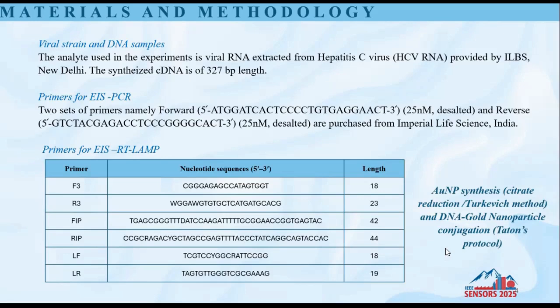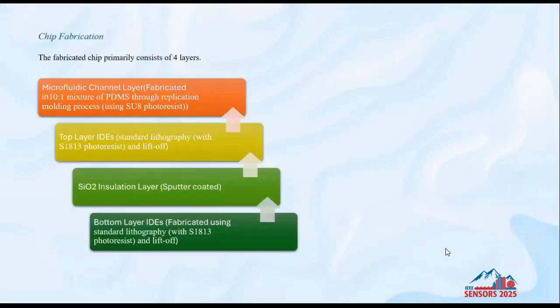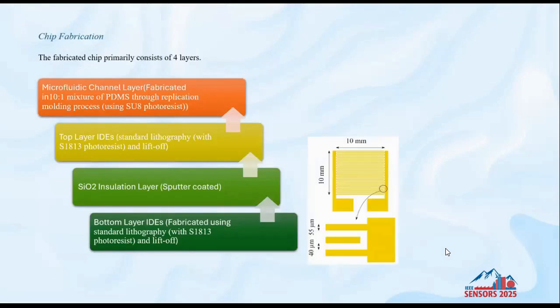As these are very standardized processes, I'm not going into the details of these steps. So then let's discuss the chip fabrication process. Our microfluidic chip consists of 4 different layers. The bottom layer, one bottom layer IDE, is fabricated using a standard photolithography process with S1813 positive photoresist and a lift-off method. After that, we have an SiO2 insulation layer to separate 2 electrode layers.